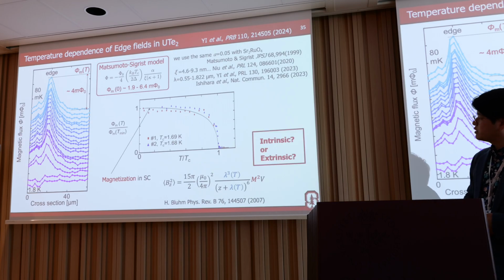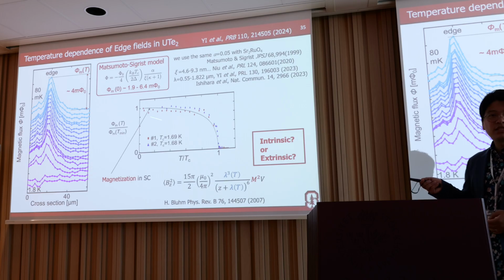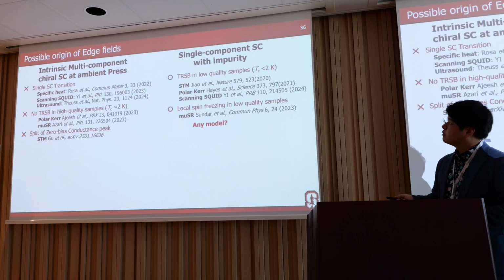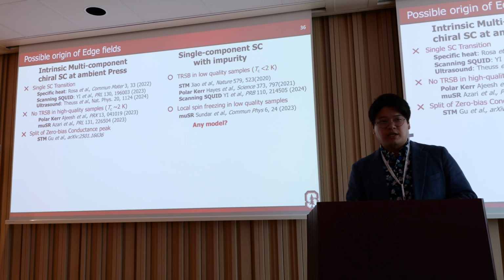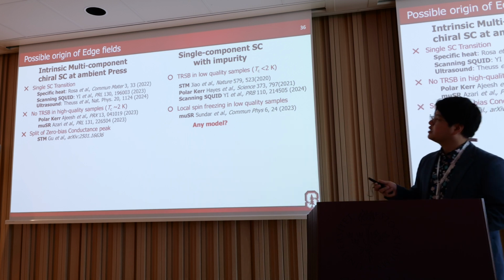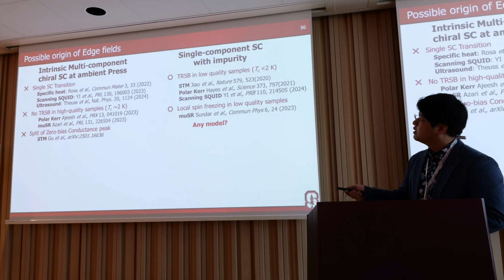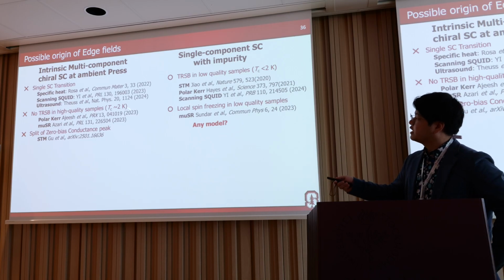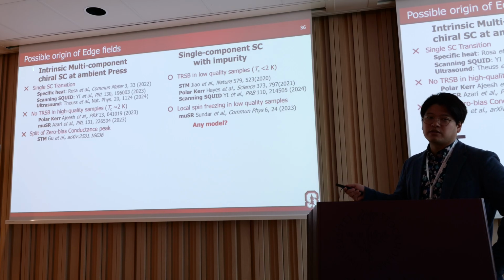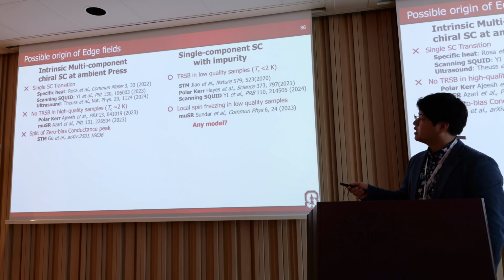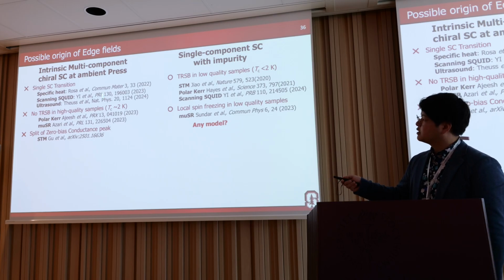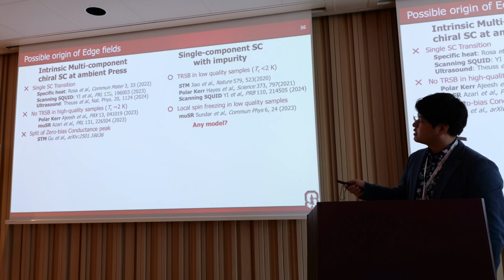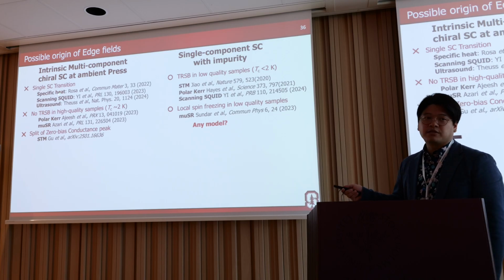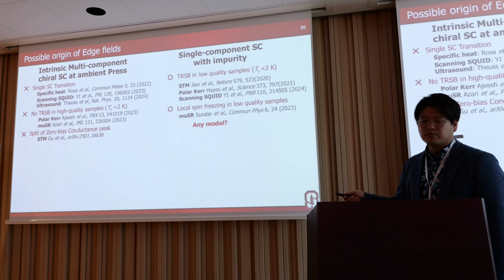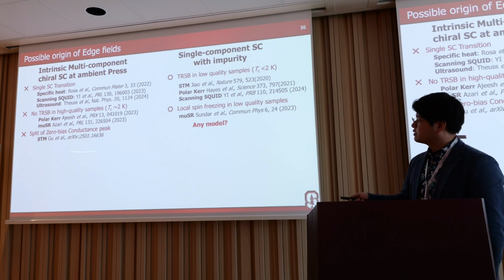But our question is whether this magnetization is intrinsic or of some extrinsic origin. Because there are some negative measurements for the intrinsic multiple components of the superconductivity. One is the specific heat, and the scanning SQUID only detects a single phase transition. But we expect multiple transitions for this crystal symmetry. And in the higher TC sample, there's no time-reversal symmetry breaking in the μSR and polar Kerr measurements, and also in STM.